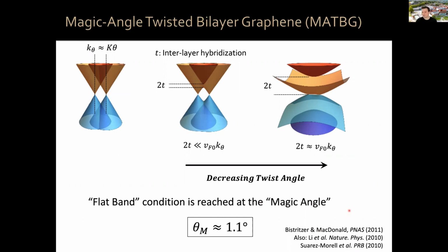At about the same time, a little bit earlier, there was also very interesting work by the group of Suárez Morell, calculating also these flat bands, and very interesting work by the group of Eva Andrei and Guohong Li on STM, looking at van Hove singularities that occur at these energies. They saw that those van Hove singularities went to 0 at about this angle. So there was a lot of interesting work on the single particle physics of this system already about a decade ago.